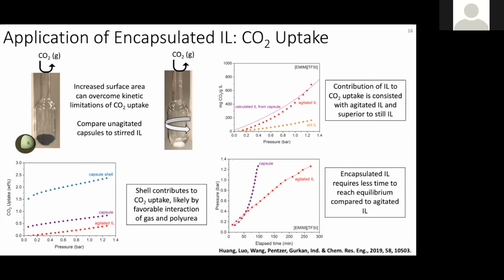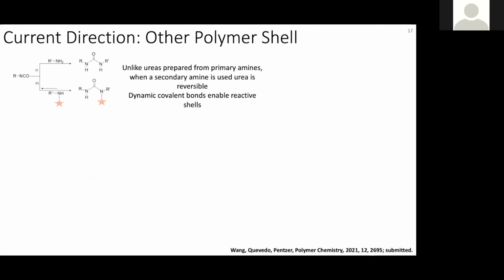We've since gone and shown that we can use a task-specific ionic liquid where you have a chemical reaction with CO2. We've also demonstrated that the identity of the polyurea shell does impact the CO2 uptake capacities. And so I'll tell you now about some of our current directions. We're interested in other polymers within the shell.